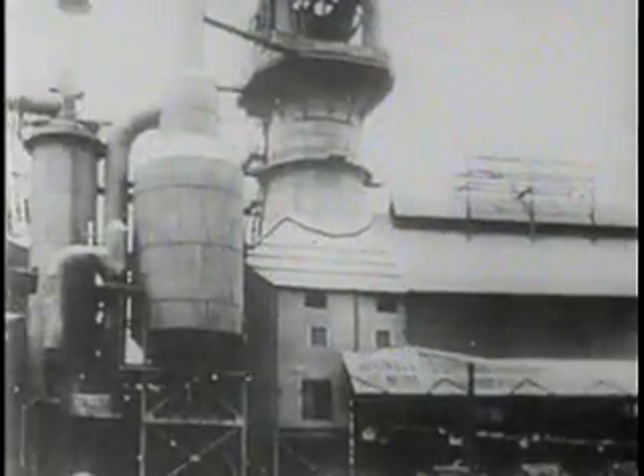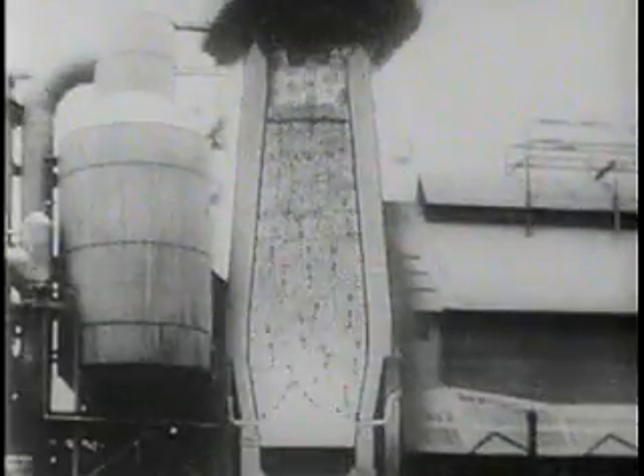With the blast furnace in operation, let's see what takes place inside. Up through the mass of coke, iron ore, and limestone is blown a roaring blast of preheated air. At the top, the temperature is about 300 degrees Fahrenheit, increasing at lower levels to a maximum of about 3,300 degrees. As the charge heats, gases formed by the burning coke draw oxygen from the ore as it descends through the furnace, leaving spongy metal similar to that produced by primitive methods.